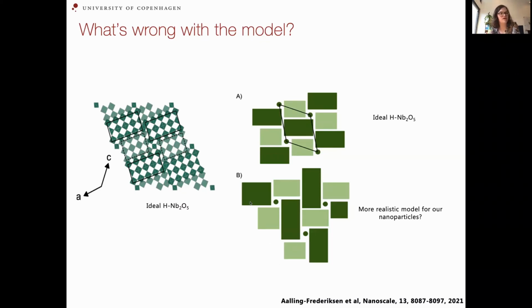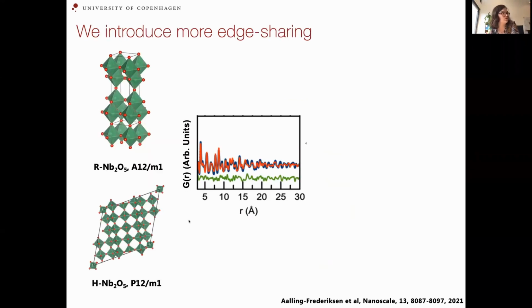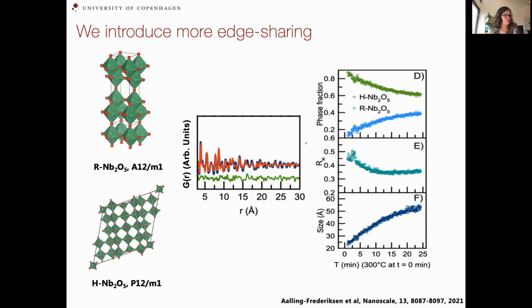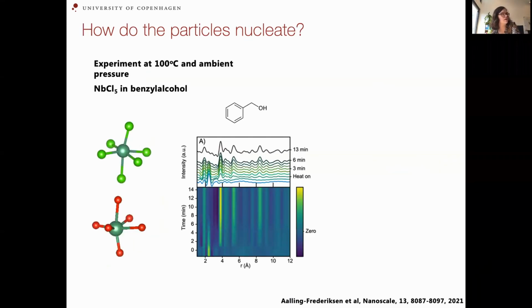So we would like to develop a simple model where we could model this. I don't have to go into details with this, but we found that by combining 2 models, representing both the inner core of these Wadsley-Roth structures and the edges around, we could actually get a fairly good description. We'll come back to this in a little bit.